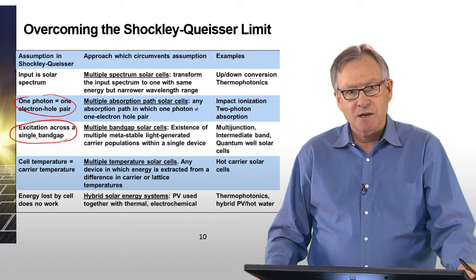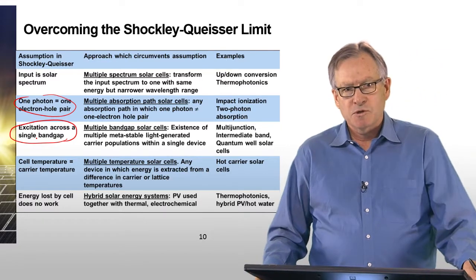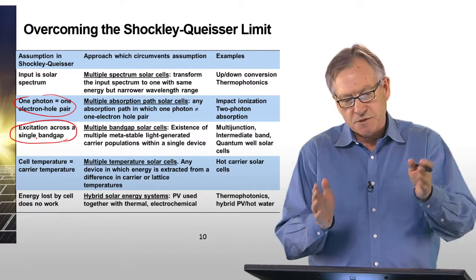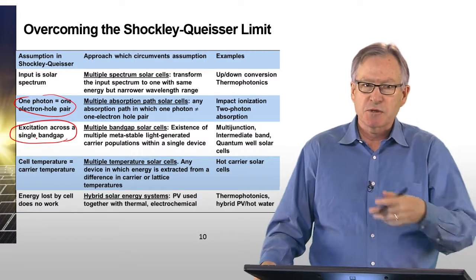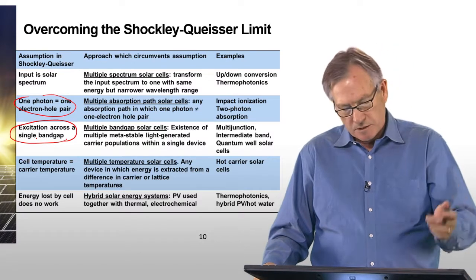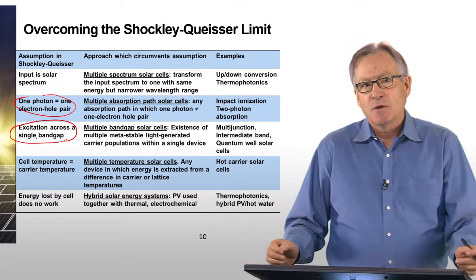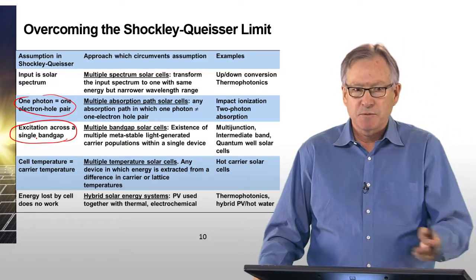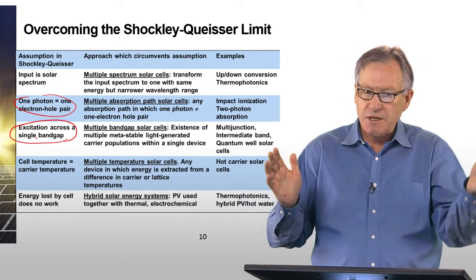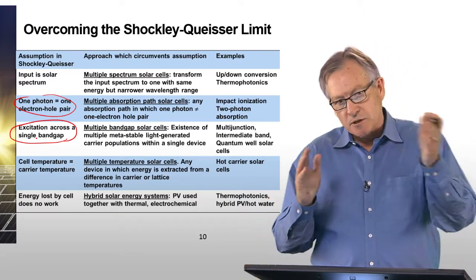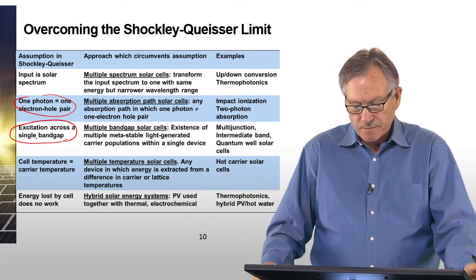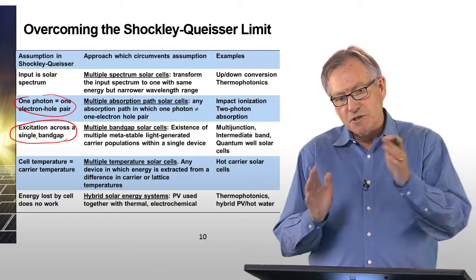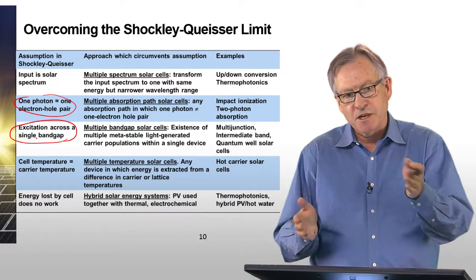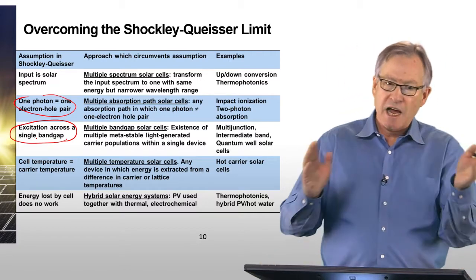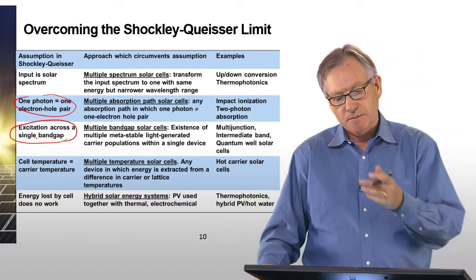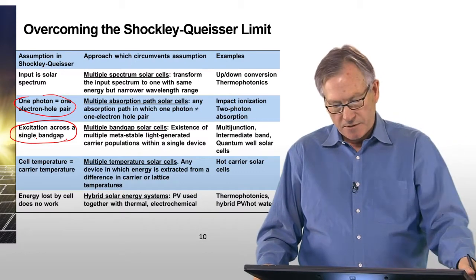Another assumption is that you have a single band gap. If you could envision a solar cell that had multiple band gaps, you could fit different portions of the spectrum to different band gap materials. And that's exactly what's done in multi-junction devices. If you have multi-band gap materials, then you can reach the thermodynamic limit. You can reach a conversion efficiency of 86% if you were able to put together an infinite number of band gaps. And we'll talk a little bit about how close you can get in reality. You can also introduce materials that have multiple levels within them. That material then acts like a multi-junction material, and will produce electricity at a higher efficiency than a single gap material.